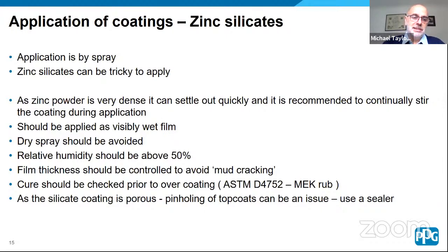Another issue with zinc silicates is, as the silicate coating is porous, you can get pinholing of the top coat, so you need to use a sealer coat. You can either use an independent single sealer coat, usually thinned down quite a lot, so that the solvent drives the air out of the porosity of the zinc silicate, or you can use what we call the mist coat, full coat technique, where you use your main intermediate coat with a very thin film to start with, and then complete the coating with a full film.